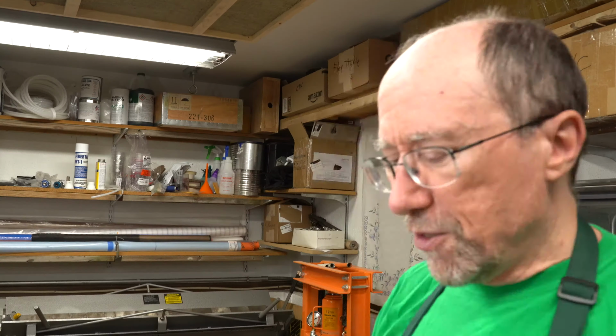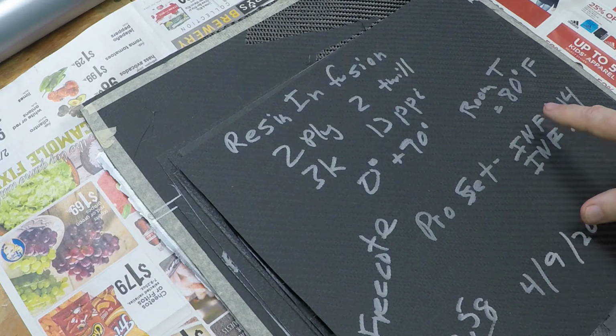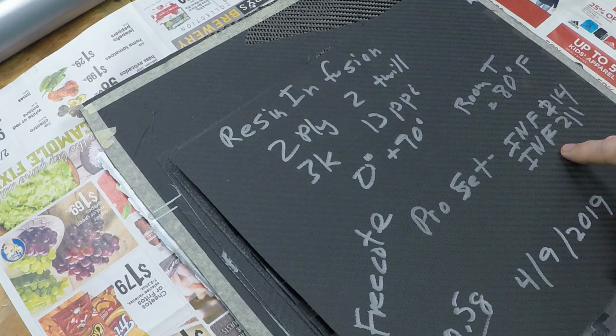Now I had been using an epoxy that wasn't really designed to do resin infusion, although if you look at the hardener, which was the Aero Epoxy pH 3663, they describe it as a structural infusion, and basically because that hardener is so thin, it thins it down enough you could use it for infusion. But I thought, well, maybe that's the problem. Let's try a different epoxy. So I switched over to a Proset epoxy, which is the INF 214 and INF 211. That's a medium cure length epoxy that's designed for resin infusion. So I thought I'd give that a try.